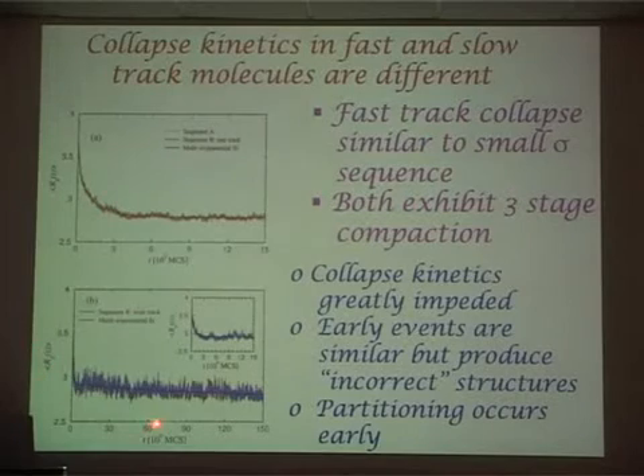This is the radius of gyration as a function of time for these slow track molecules, the ones that get caught in the competing basin of attraction. Notice this time scale is 150, about 10 times greater, and even so it has still not reached the maximally compact structure because it has not fully overcome the barrier. So collapse is impeded. Early events are similar in the fast track molecule and the fast folding sequence. The partitioning occurs. Okay, that's only for biochemists.